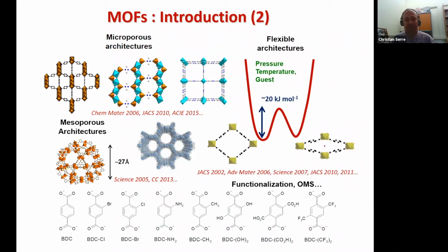And you can have, in some cases, flexible architecture where the porosity is dynamic, meaning that you can change the pore size, the pore aperture, by simply applying a stimulus. You need to overcome an energy barrier here. And the stimulus can be, of course, gas molecules, but also temperature, pressure, even light. There are many possibilities. And this increases the complexity of the structure at the end, but it increases the possibility of different applications based on this dynamic framework.